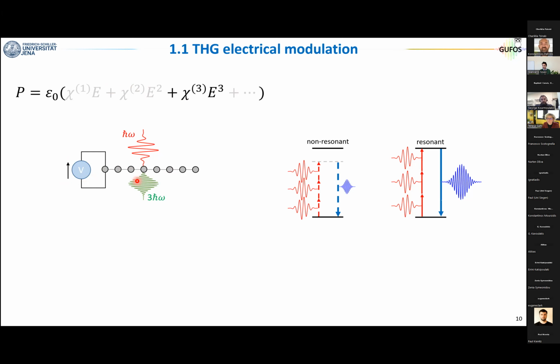Now imagine that you take a gas or a semiconductor, and you do your third harmonic process. So you arrive with 3 photons and generate 1 photon at 3 omega. Now this process can be either non-resonant, and this is the case where the final state of your nonlinear process is a virtual state that lies within the gap, or it can be resonant. In this case, with your multi-photon, you hit a real electronic transition, and in the resonant case, you will have a huge enhancement of the nonlinear optical response of your material.